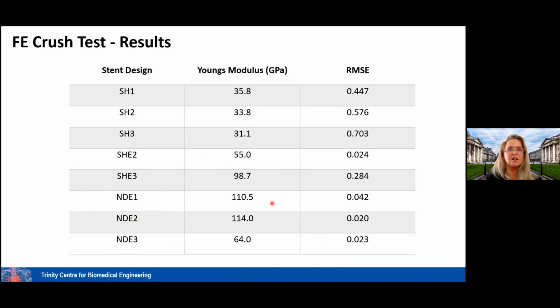we saw experimentally. And what you will note here, particular note, is that for the simple honeycomb etched and the novel design etched, while there is some variability, we have close to, up around 100 gigapascals for Young's modulus, which we would expect for something like a 3D printed titanium to be lower than the bulk or as cast material, but not to be as low as this. I mean, to see 31 to 35 gigapascals as a Young's modulus, this is very strange because this would be very low for titanium.